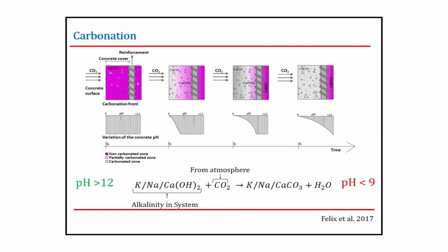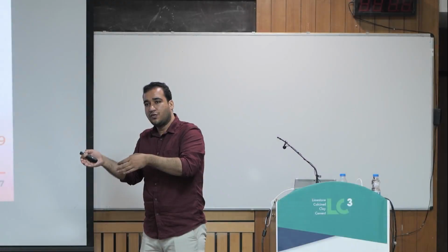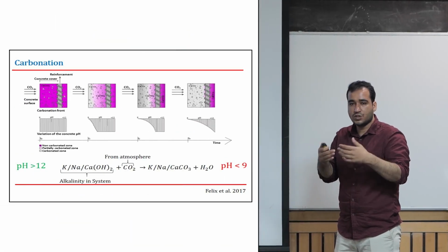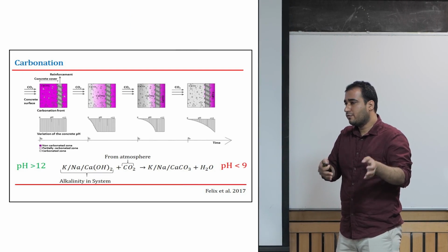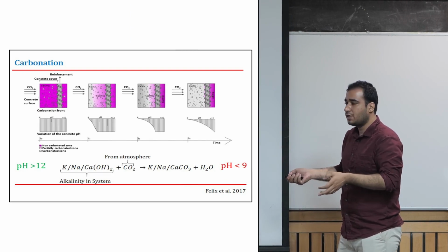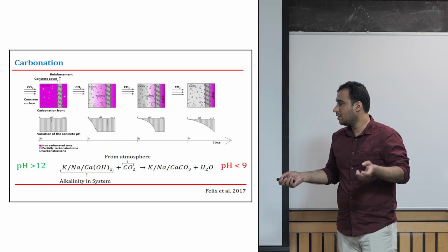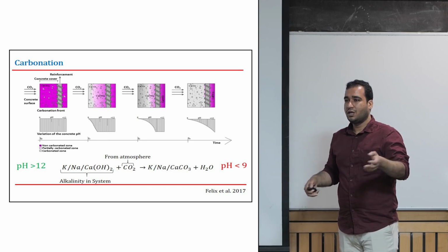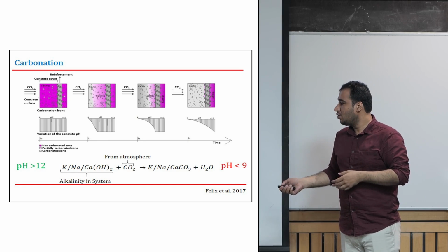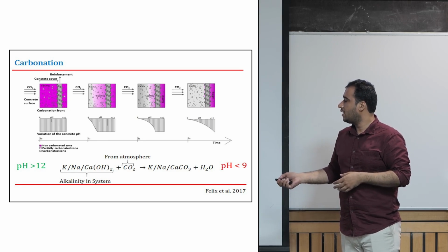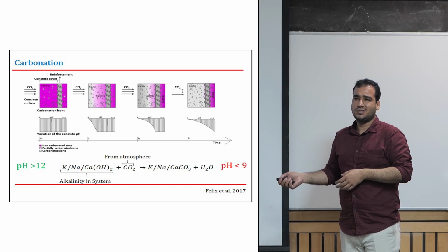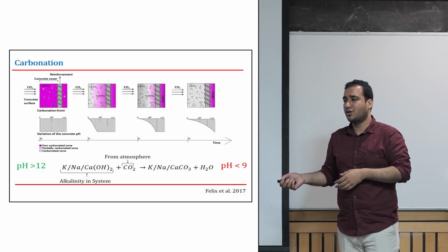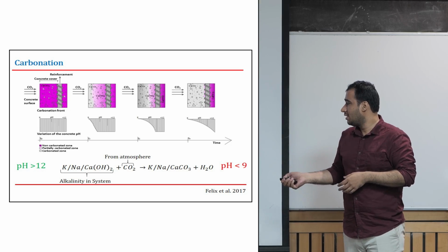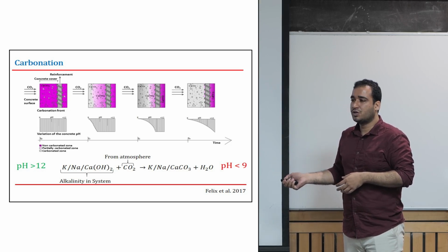Like I told you, carbonation is the process where atmospheric carbon dioxide gets into the concrete through the voids that contain air, and it meets the water, dissolves into the water, and forms carbonic acid. Now, concrete, I guess everybody knows, has calcium hydroxide, Portlandite, sodium, alkalis, Na2O equivalent. We all calculate this. All this reacts with the dissolved carbon dioxide and forms carbonates. Carbonates don't like to dissolve. They like to get out of the system. They start to precipitate, and their precipitation means calcium is also getting out of the system.